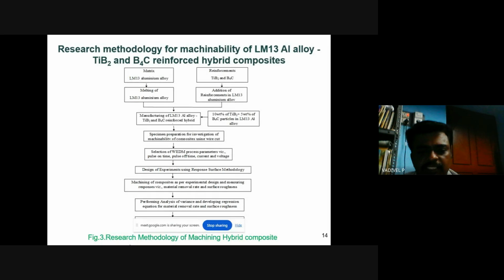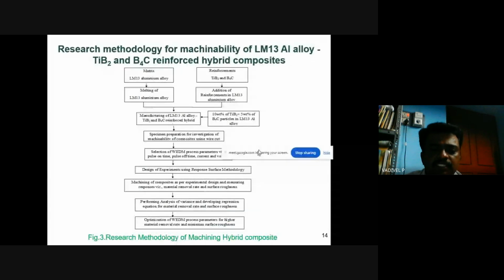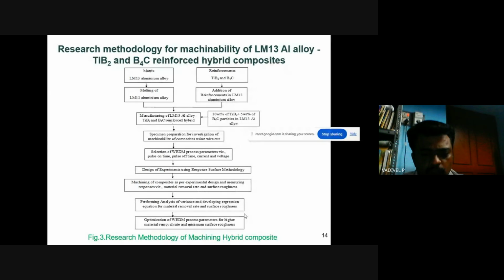Then after doing that, the DOE, design of experiments, using RSM, response surface methodology, has been done. Then machining of the composite as per the experimental design, and measuring the responses, namely the material removal rate and the surface roughness. We have done the analysis of variance, the regression analysis using the ANOVA table, and developed the regression equation for the material removal rate and the surface roughness. Then finally, we optimize the wire EDM process parameters for higher material removal rate and minimum surface roughness value.